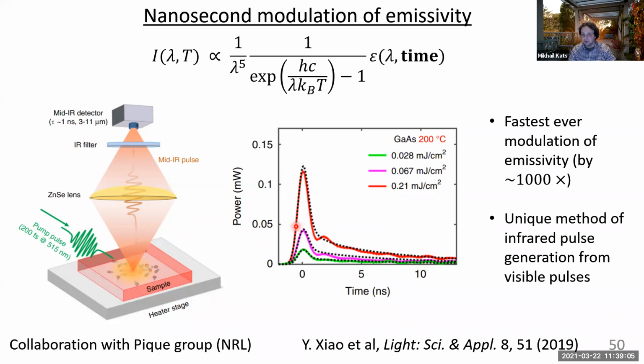So this peak is actually not supposed to be this big. Just from the change of emissivity, it's supposed to be only about this big, but it becomes bigger because you have this very short, picosecond-scale pulse that we can't measure. That's just being convolved by the response function of your mid-IR. Exactly. So you could deconvolve, I guess, but I don't think you can deconvolve a picosecond feature from a nanosecond one. I see. So actually, things like this happen in graphene all the time.